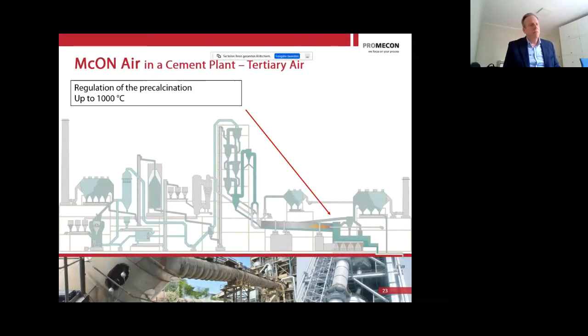Now, tertiary air, as I mentioned before, is probably the harshest and the most difficult application, but a very important one. You have NOx formation in the main burner, you have NOx formation in your precalciner, and you try to avoid both. So what you have to do now is you have to have the right amount of total air coming from the clinker cooler. Main part of the air goes into the rotary kiln. Some of the air goes into the TAD. Now you want to reduce the total air on the burner so that you get a low NOx formation on your main burner. At the same time, you do not want to draw too much tertiary air into your precalciner so that you have a lot of NOx formation in that calciner.